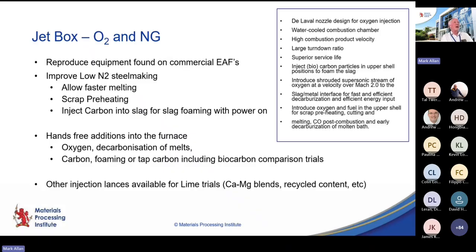And also the fact that we now have those as automated functions through the sidewall of the furnace means we can get away with some actions that had to be manually introduced in the previous furnace, where to do oxygen injection or carbon injection, we would have to stop the process, open the slag door, and introduce lances through the open slag door.